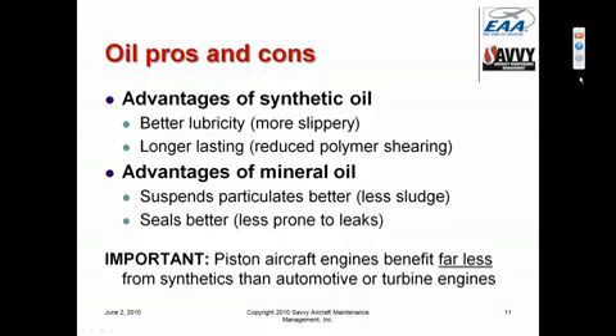The advantages of mineral oil are that it does a much better job of holding particulate matter in suspension, so that we can drain it out at oil change time rather than having it form sludge inside the engine, and that's particularly true of lead sludge. And mineral oil, because of its branchy structure, seals a little better when we're dealing with things like gaskets and O-rings. Synthetic oil tends to sneak by those things a lot more, and so we see a lot more leaks in engines run on synthetic oil than we do on mineral oil.